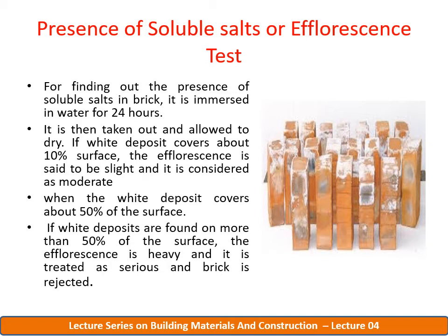The experiment is performed in a well ventilated room between 20 to 30 degrees centigrade till all the water in the dish is either absorbed by the specimen or evaporated. After the specimen has dried, add a similar quantity of water to the dish and let it be absorbed by the specimen, then check for efflorescence after the second evaporation.